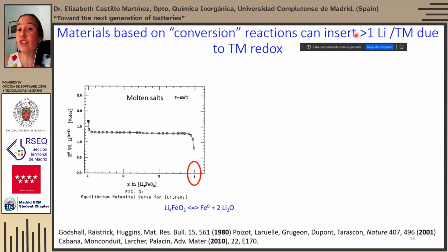Another type of material that has called lots of attention are those materials based on conversion reactions. They can insert also more than one lithium ion per transition metal, but in this case, all of the reactivity is due to the transition metal, to the redox properties of the transition metal. Here you can see a plot in which in the 1980s already, the insertion of up to 4 lithium atoms in lithium iron oxide, in the layered lithium iron oxide, takes place. And if we look at the chemical formula, we can actually see that here the iron oxidation state is 0. And what happens is that we actually have iron 0 and lithium oxide.